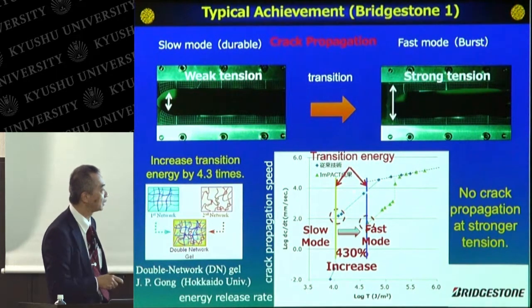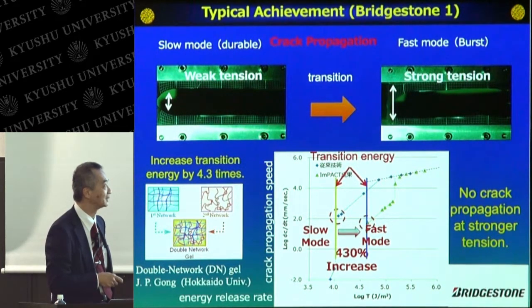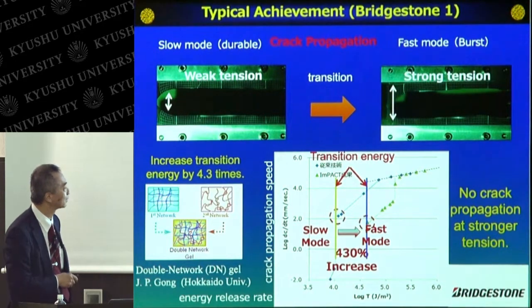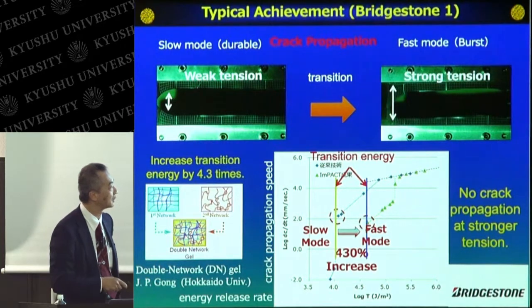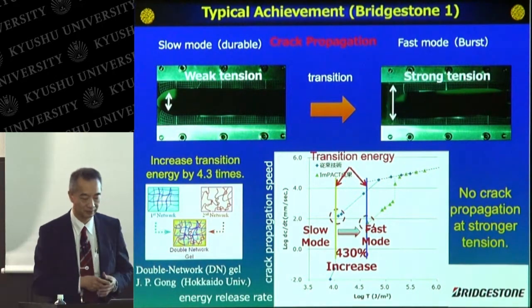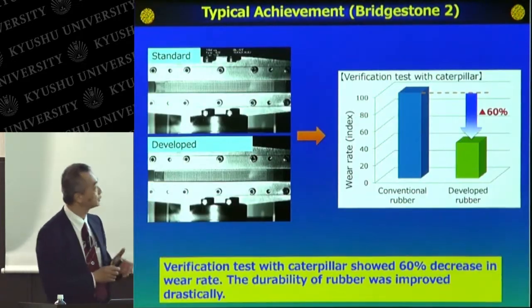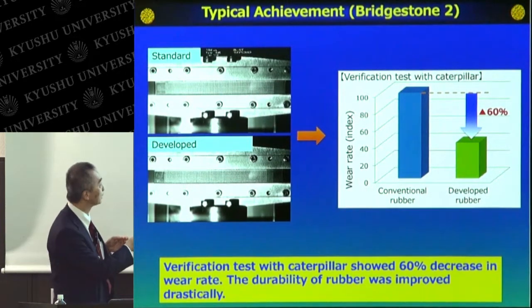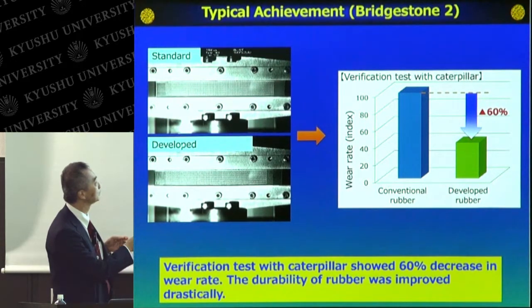So Bridgestone tried to increase the threshold transition energy to a higher energy area. So they finally used the concept of double network gel by Professor Gun at Hokkaido University. They finally increased the transition energy about 4.3 times. Then no crack propagation occurs at stronger tension. So this shows the results. So this rubber is a standard one, and this is a developed one.